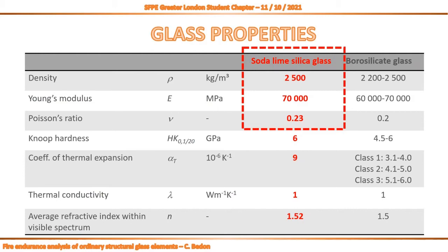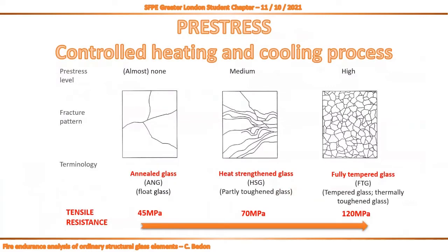But we should also mention, before moving to fire, that we can take advantage of heating and cooling stages during the production phase, in which, okay, we know that the glass is very brittle in tension, but we can also improve its basic mechanical features. And so you will probably hear here about annealed glass, which is the basic solution in which the tensile resistance is in the order of 45 megapascal. We can apply a partial pre-stress stage and increase this tensile resistance up to 70 megapascal. And for sure, the best solution is the fully tempered glass solution, in which you can see that the tensile resistance is in the order of 3 times the simple annealed one.